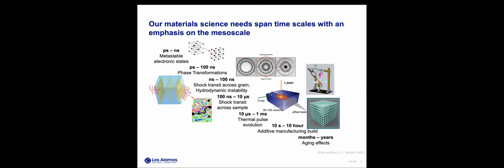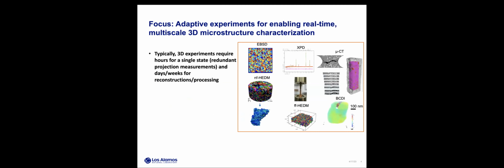And despite these goals, we still can't perform these multi-scale measurements at both relevant time scales on a single sample. This is pretty much our grand challenge, as these measurements are crucial for developing and validating multi-scale models for bridging both the length and time scales that span several orders of magnitude. Thanks to facilities like APS, we now have sophisticated techniques that can enable us to investigate 3D mesoscale materials across multiple length scales. However, obtaining detailed 3D microstructural imaging of polycrystalline materials is still a challenge and requires hours for a single state measurement.